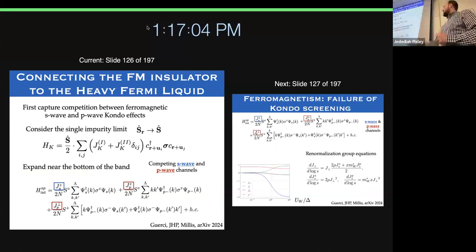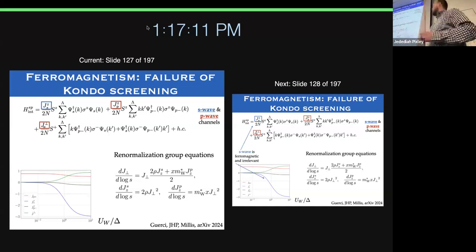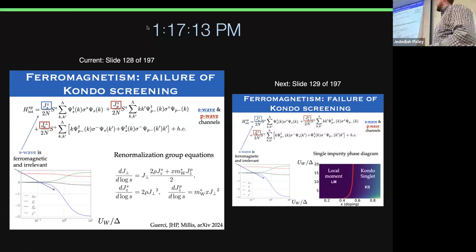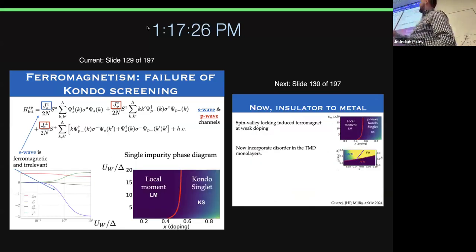S wave could be relevant if it's antiferromagnetic. But as you can guess, as I already showed you, it's going to be ferromagnetic. And so the ferromagnetic interaction is irrelevant. So the local moments don't bind to electrons at low density. They have to go through a critical value where the P wave Kondo coupling is large enough. And so you find a phase diagram like this for the local moment.